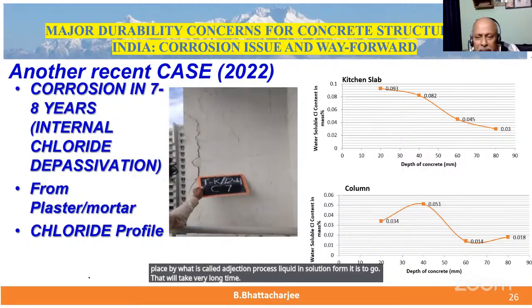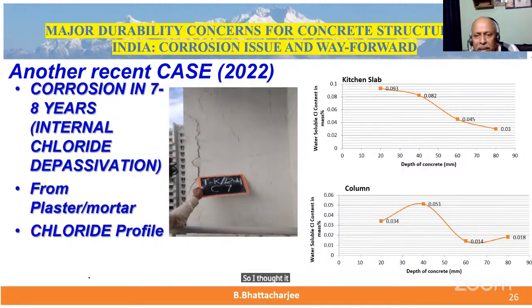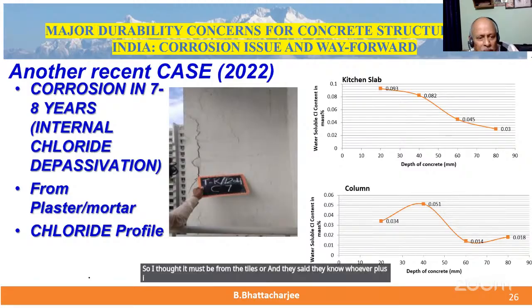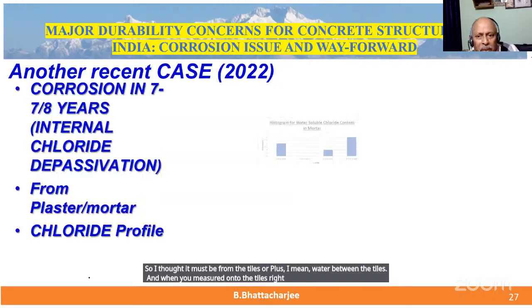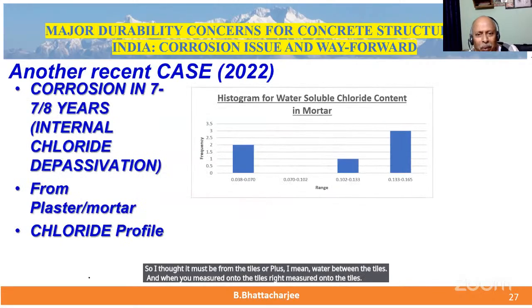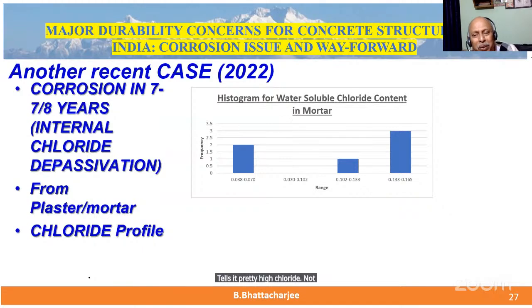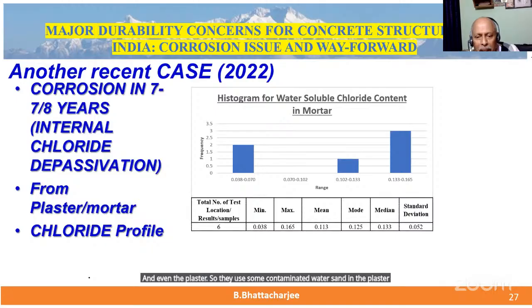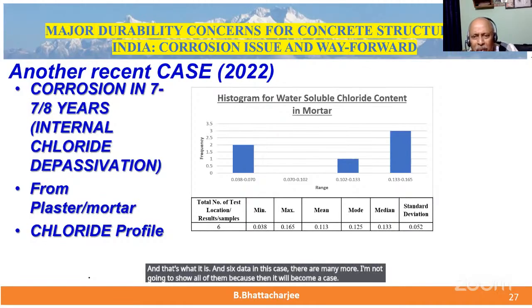So I thought it must be from the tiles, and they said then we have a mortar between the tiles. And when you measured onto the tiles, right, measured onto the tiles had pretty high chloride. Not tiles, the mortar between the tiles. And even the plaster. So they use some contaminated water, sand in the plaster or mortar. And that's what it is. And 6 data in this case, there are many more. I'm not going to show all of them because then it will become a case. I don't want to do that.